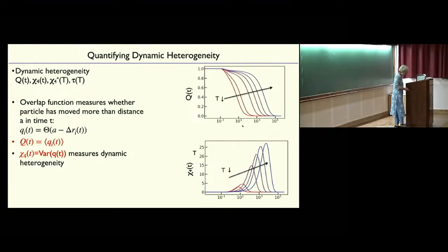So how do we quantify that dynamic heterogeneity? Well, we quantify it by this thing called the overlap function. The overlap function just measures whether the particle has moved more than some distance, which is usually taken to be a fraction of the particle size, in a certain time. So it's 1 if it hasn't, it's 0 if it's moved more than that distance. And when you average over all the particles, you get the average overlap. At high temperatures, it'll decay quite rapidly because at first nobody has moved, but rather quickly everybody moves. And the time scale that governs this decay is the relaxation time. As you cool the system, that relaxation time gets longer and longer.